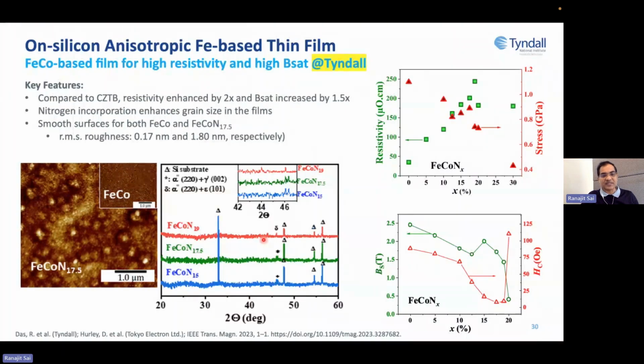How we can get about that. So we have deposited some iron, cobalt, nitrogen based magnetic material, and after thorough material search and development and process tuning, what we have found here is that the resistivity of the film can go up to 200, whereas the standard CZTB is 100. So it's 2x more resistive, and its stress is also quite low.